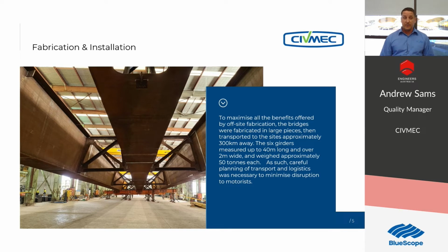Once the trial assembly was complete, the individual girders were placed in our large blast and paint facility to be blasted to a Class 2.5 profile. That included the outside surface, which isn't painted, and the inside surface has system SC5 applied. SC5 is a three-coat system, with the final top coat being white in colour. Once the paint application was complete, the girder segments were taken out into the yard and had three cycles of fresh water applied over a three-day period. This process helps aid the superficial rusting in a uniform manner.